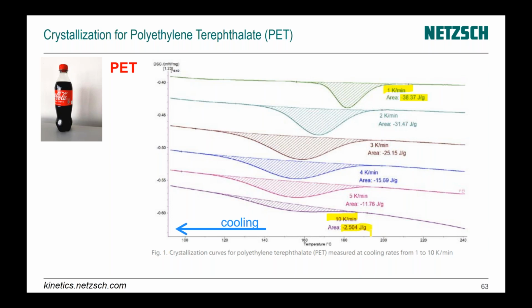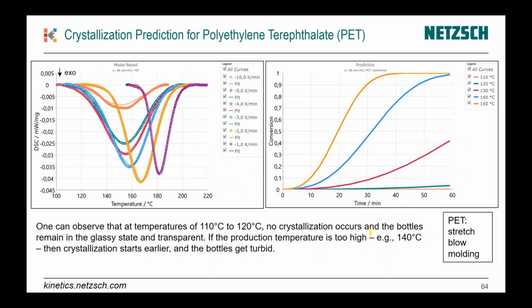Why? Because for fast cooling, there is no time for crystallization. We put this data into the software, and our software, the Nakamura model, can describe not only the shape of this material, but can describe the difference in the peak area.